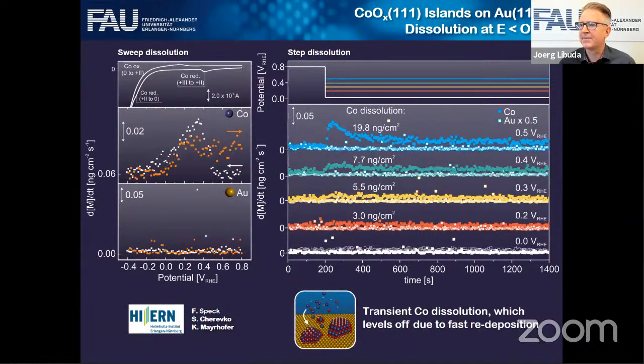So under the same conditions, we do scanning flow cell mass spectrometry experiments and measure the dissolution rate when we go from the stability region to different potentials where the cobalt oxide should not be stable. And what you see is, if you jump into this region where you see this onset of mobilities, where these islands start to move, then you get a strong transient dissolution.